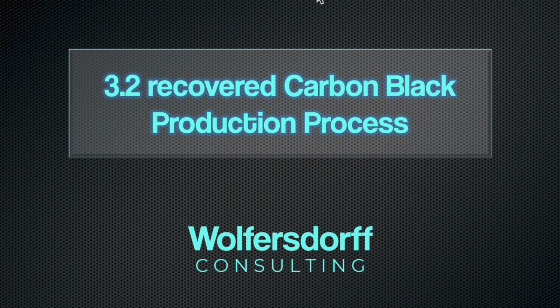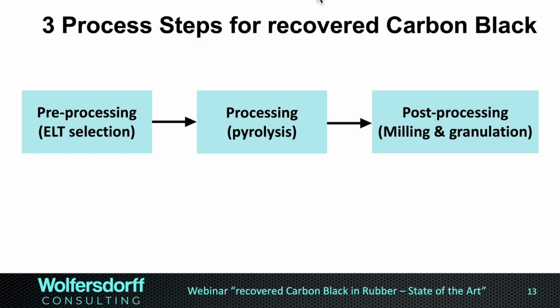Let's look at the production process. And again, I see a three-step process for the production of recovered carbon black, where in the past, maybe people have seen the pyrolysis as the main process. I already got some comments on my presentation at the ETRA conference where I said, look, the pyrolysis really doesn't contribute that much to the quality of the recovered carbon black. It doesn't when you look at this process scheme. For me, the process for recovered carbon black starts with the selection of the tires. Then we have, of course, the pyrolysis, and then we have the post-processing, which includes both milling and granulation, and also the taking out of the remaining steel particles by magnetic means.